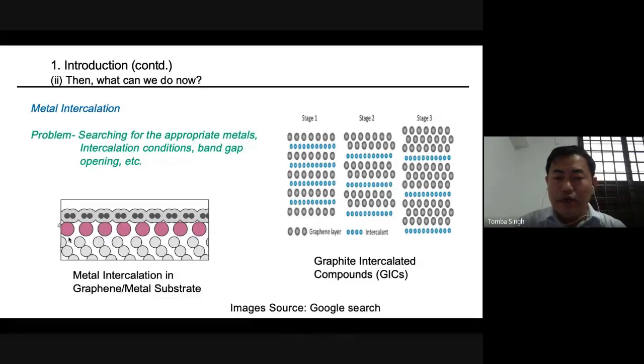In this picture, we see the intercalated metal layer, these pink balls, below the graphene layer, the black balls, and above the substrate, the gray balls. So this is the picture representation, but there are many problems. We have to search for the appropriate metals and the different intercalation conditions. And one of the reports is that it opens a band gap. If it opens a band gap, then the intrinsic property will be affected.